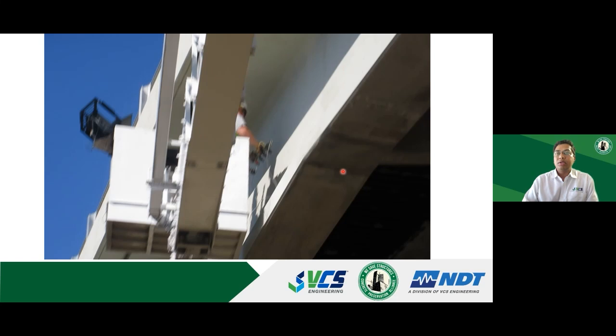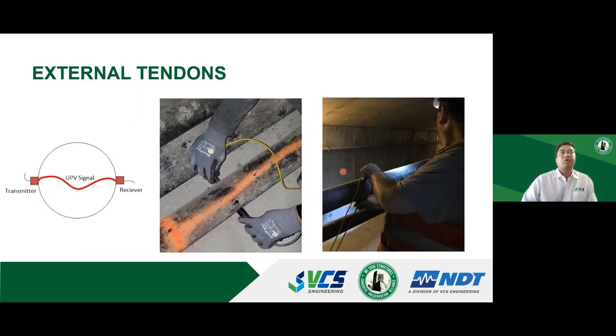So you lay out the tendon, you do the impact echo testing, and this is the system we use for internal tendons. We can use a similar system for external tendons where you have a transmitter and a receiver on the opposite ends of the external post-tensioning duct, and you send a signal from the transmitter and you receive that sound signal from the receiver.